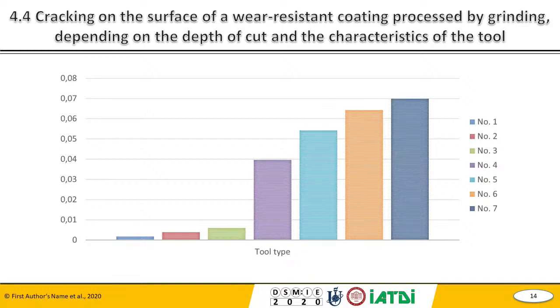Various grinding wheels were used to determine the dependence of crack formation on the depth of cut and the characteristics of the tool. The distribution of cracks on the surface of the wear-resistant coating treated by grinding, depending on the depth of cut and the characteristics of the tool, is shown in this figure. The figure shows that the most productive tools for processing wear-resistant coating while maintaining its quality characteristics are number 6 and number 7, which allow us to process the surface at great depths of cut. Next slide, please.